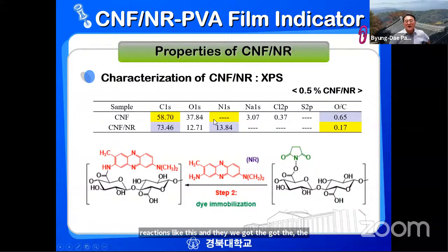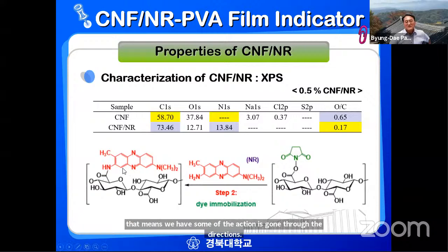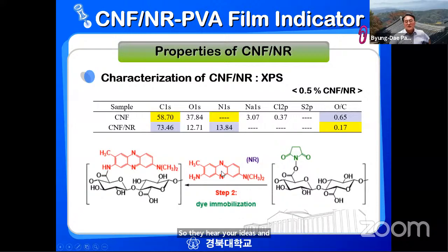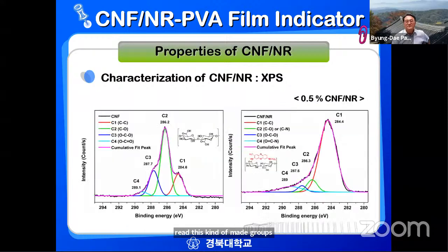the carbon 1s, oxygen, and obviously CNF has no nitrogen. So sodium, chloride a little bit, no sulfurs. But with neutral red, we have carbons, and also obviously we have nitrogen, and our oxygen is decreased. That means some of the oxygen has gone to the reactions. So here, I will say the nanocellulose has reacted with the neutral red, forming these amide groups, amide bonds, I would say.